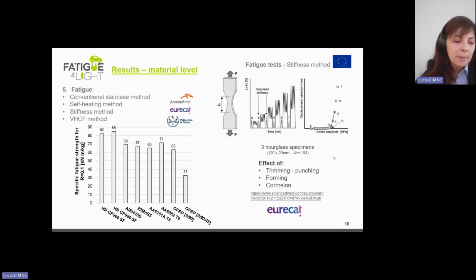I just want to say that an interesting information for you to take from this presentation is that, for instance, a typical fatigue experimental campaign performed with the staircase method would last about 2 weeks. With these fast fatigue testing methodologies, you can reduce the testing time to about 4 hours, okay, and with only 3 hourglass specimens, and you will have the fatigue limit. So it's a very interesting